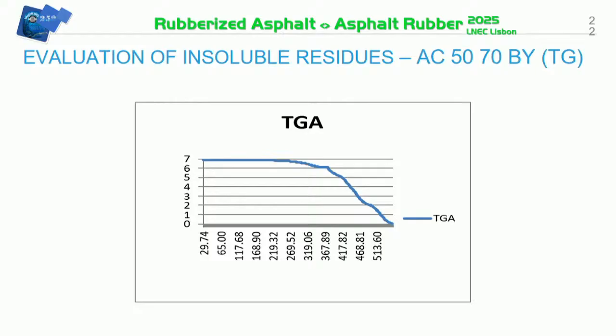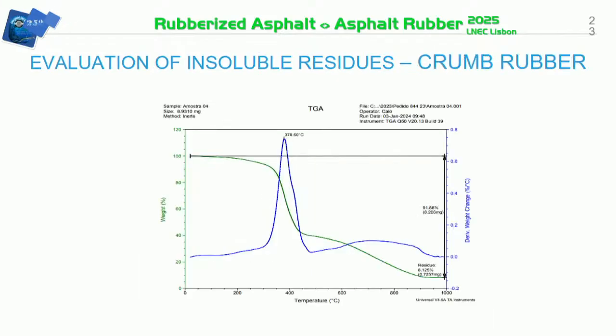These results were confirmed by the thermogravimetric analysis (TGA) test: test 1 for asphalt cement, test 2 for crumb rubber.